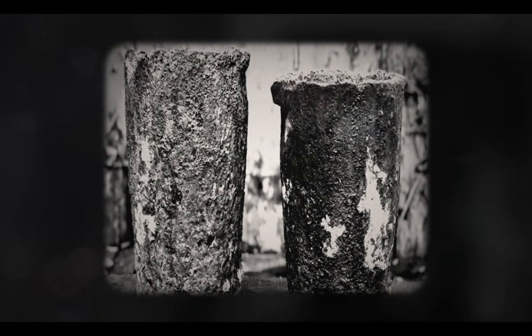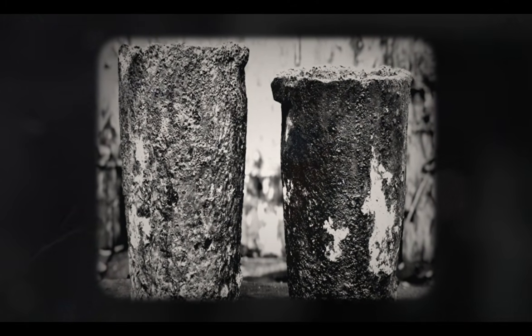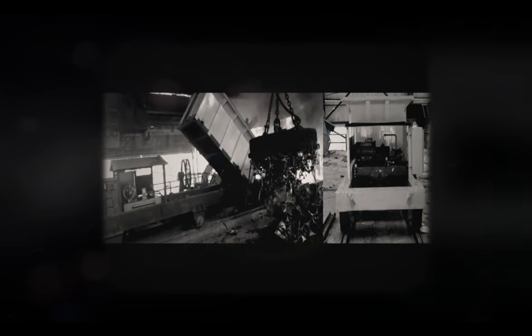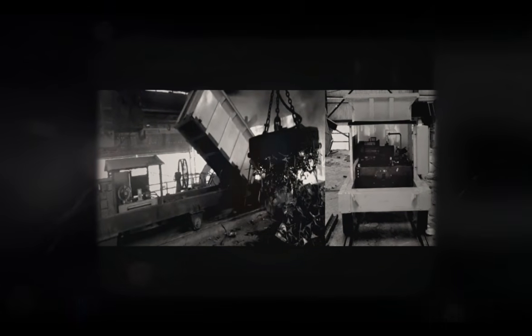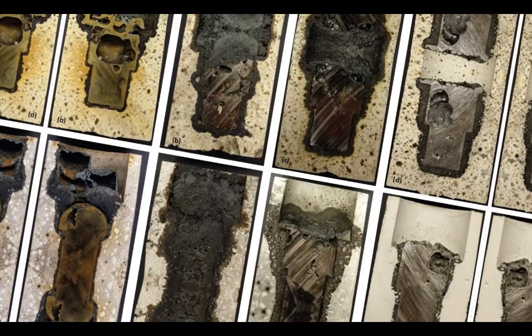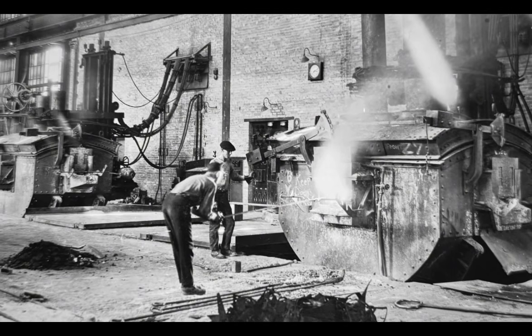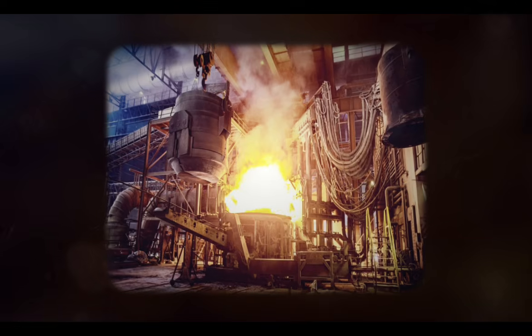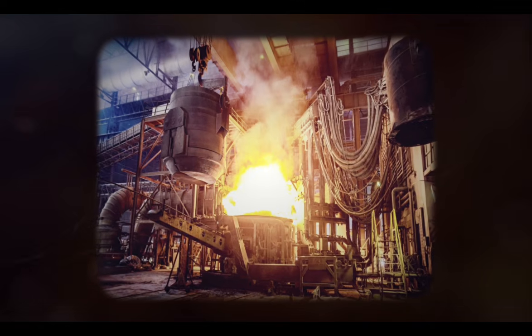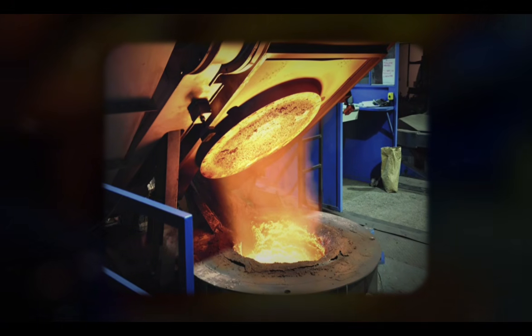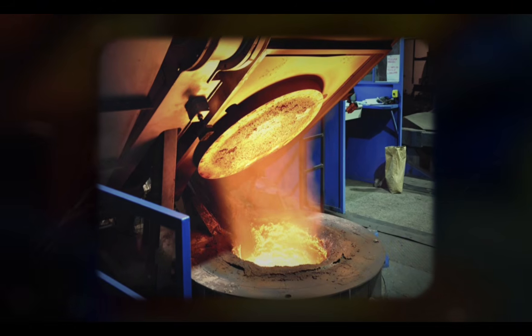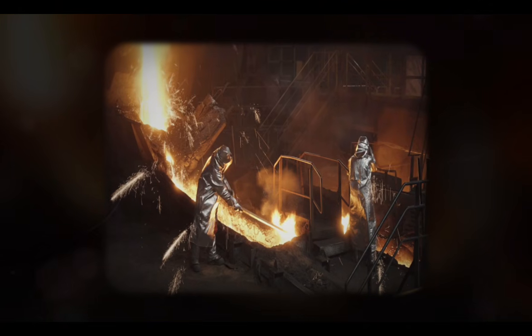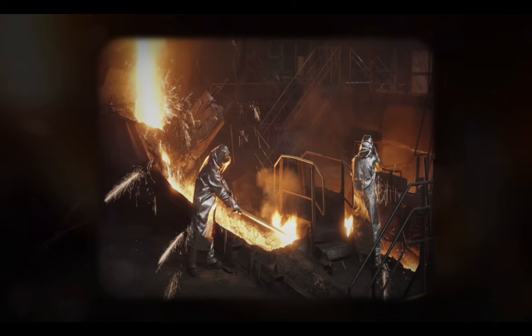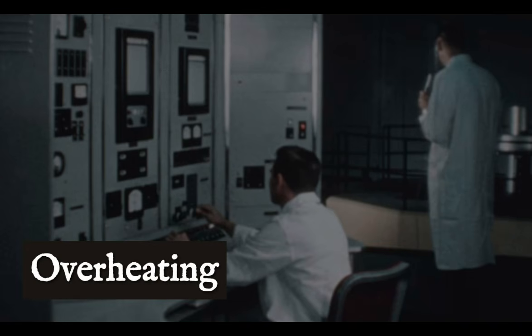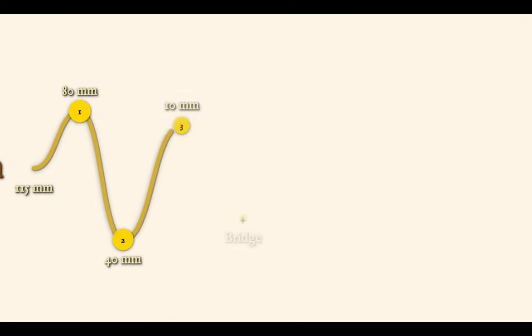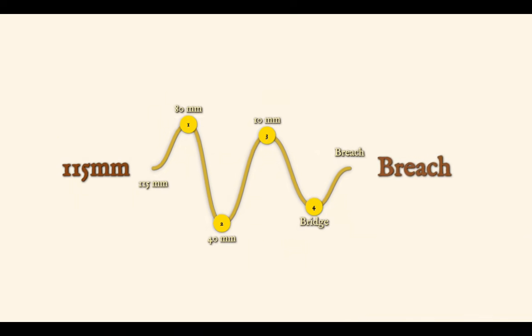But the bridging hazard introduced a second path to the same failure. When solid charged material, scrap steel or alloyed stock loaded into the furnace, failed to fully melt into the pool below, and instead formed a bridge across the upper section of the crucible, a gap opened between the bridge and the molten metal beneath it. The lower bath, still under full electromagnetic power, continued absorbing energy with no cold charge above it to moderate the temperature. It superheated. At temperatures well above the designed operating range, the lower lining eroded at a rate that could breach containment in a single heat cycle.